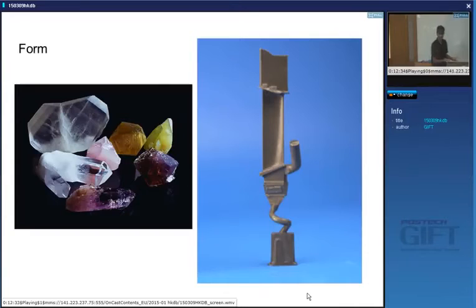And in the turbine blade, you actually grow the blade along a specific direction so that the elastic modulus is such that you reduce vibrations. You want as few vibrations inside an aircraft engine as possible. So you can exploit not only the fact that you don't have grain boundaries, but also that you can grow along directions which will minimize vibrations during the operation of the engine. Okay. So typically this might be rotating at 25,000 revolutions per minute inside an aircraft engine. So if you have vibrations, that's not a good thing.